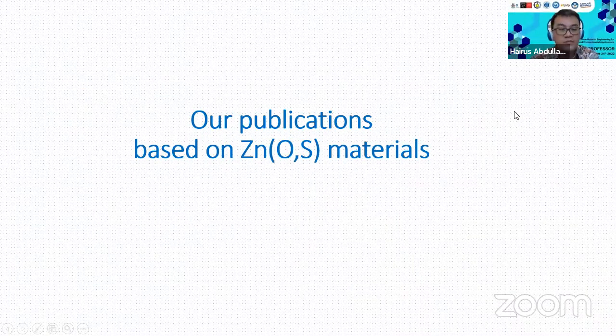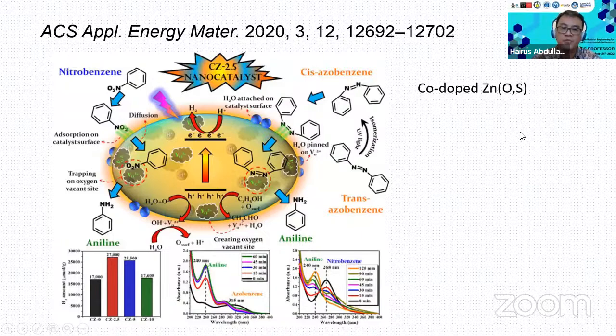Okay, then I'll show you some publications related to the Zn(O,S). We have published some papers related to this Zn(O,S), and it can also be used for hydrogenation reactions. The first one is the cobalt doped, as we discussed in the previous slide with a very simple characterization. We have cobalt doped into the Zn(O,S), and it shows that the hydrogen evolution reaction is quite high here. It can also be used to hydrogenate nitrobenzene to form aniline, and azobenzene to form aniline.